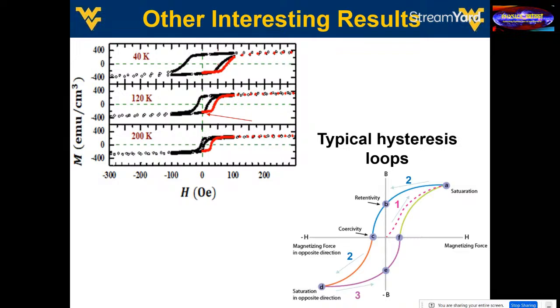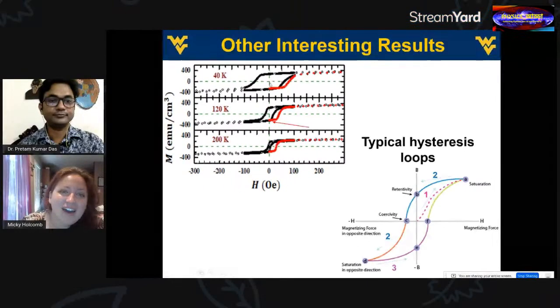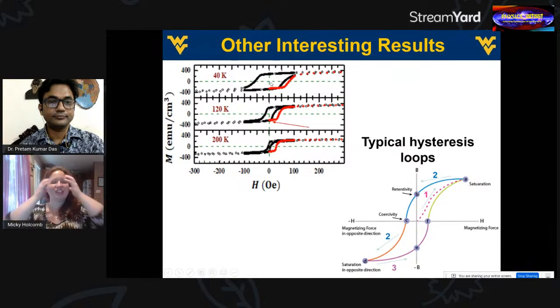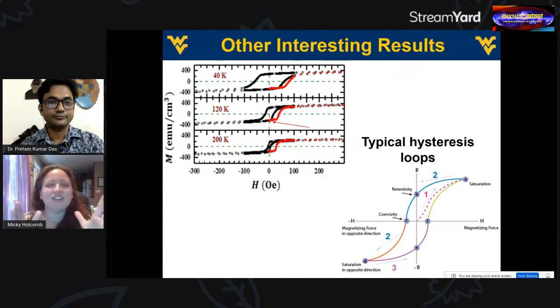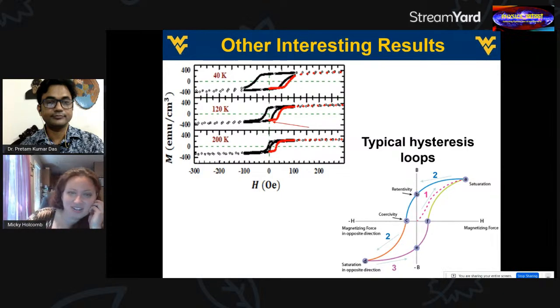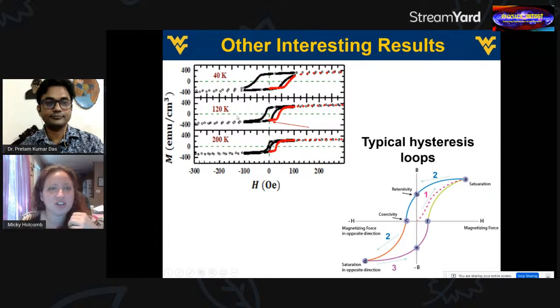And the first thing you'll notice is it doesn't start from zero, right? When we turn on the field, we immediately have a magnetization and it's negative, right? So as soon as we turn on a field, this magnetization wants to point opposite to it. So we have an initial negative magnetization as soon as we turn on a small field, right? It's not very big yet, small field. And this is shown for various different temperatures.